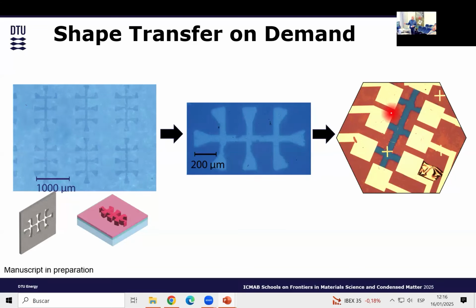That was strontium titanate doped with niobium, and we cool it down and measure the properties. It's exactly the same as when we compare with another material grown on normal STO. So it's a way of having materials in a different shape, a different orientation also, which could be interesting for many applications, in my opinion.